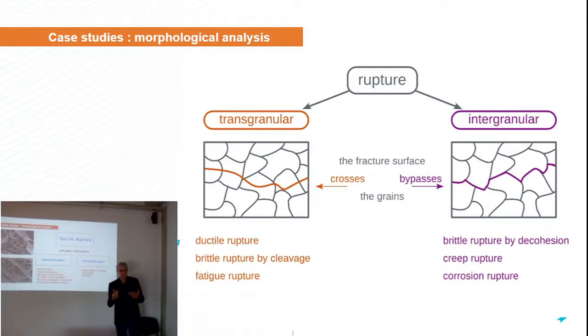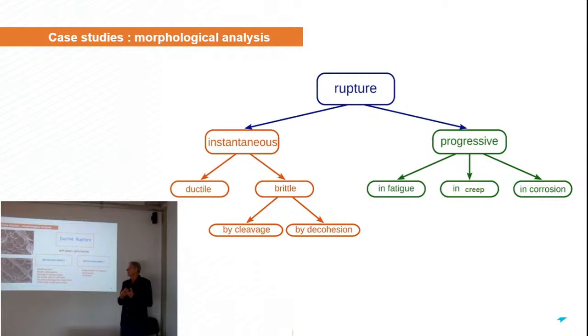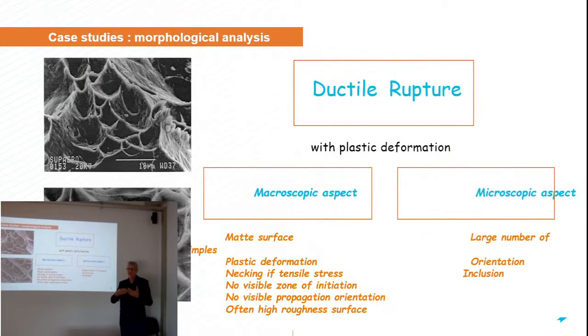So it is interesting to check here, either by observation or by the kinetics of rupture, what type of rupture you have. These are the main characteristics of ductile rupture. You have always or often plastic deformation close to the surface, and in the macroscopic aspect you can find a matte surface, plastic deformation, necking if the applied load is tensile, no visible zone of initiation and propagation, and often a high roughness surface.